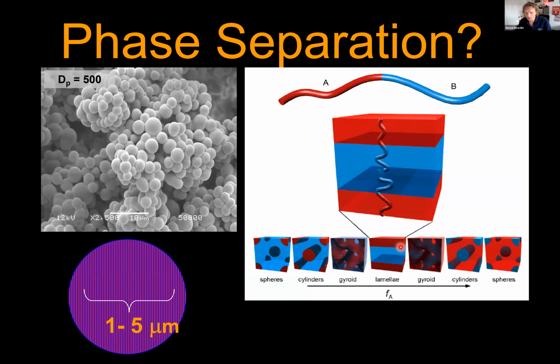So we then moved on to trying to create some block copolymers. And this is quite interesting. If you create block copolymers, you can make a run of A and then add monomer B. And what you try and do is choose A and B so that they hate each other, they don't want to mix. And so the polymer will self-assemble and will form zones of B surrounded by zones of A.